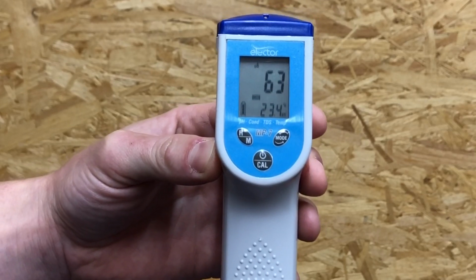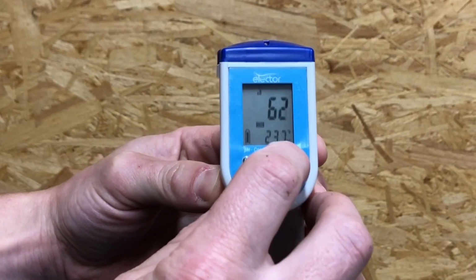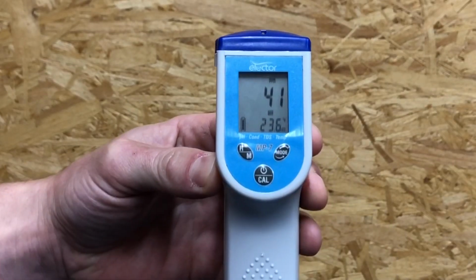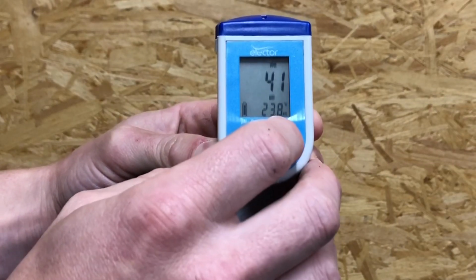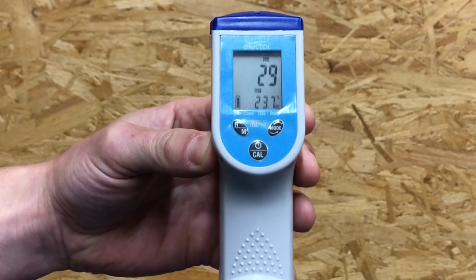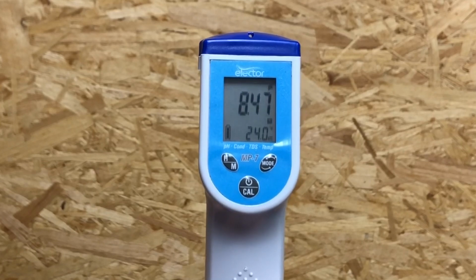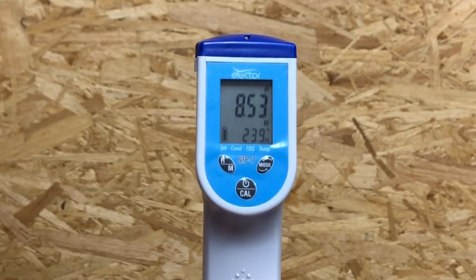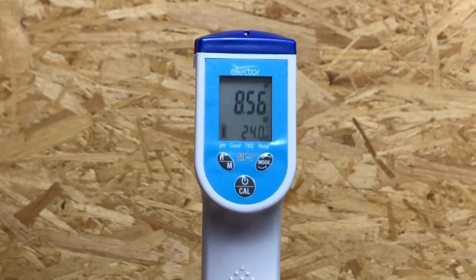So our conductivity now is 63 microsiemens. Our TDS has dropped to 41. And our salts are at 29. So we're now measuring the pH. And our pH is about 8.5, 8.6 again.